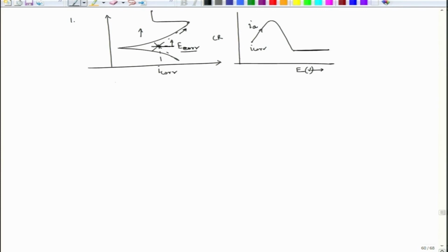The other nature is, let us say, a change in concentration. So, the corrosion rate, CR, is plotted with concentration. For example, in the very experiment that Faraday did, if we put an iron block in dilute HNO3, the corrosion rate would be high. As we increase the concentration, we keep getting an increase in corrosion rate, but at some critical level we see that the corrosion rate suddenly drops.